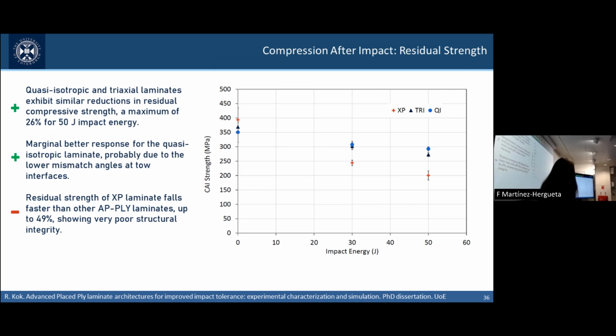There is a marginally better response of the quasi-isotropic laminate, and that's probably related to the higher spread of angles that we are using. That's something that is also extrapolated from general angle-ply laminates. We have seen that on low velocity impact, they tend to behave better when there is a smaller mismatch angle between layers. This is something that we are also evaluating here. Marginally, the quasi-isotropic laminates have a lower mismatch angle between tows, and that results in better stability and a lower delamination footprint.